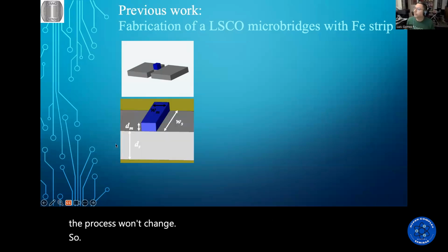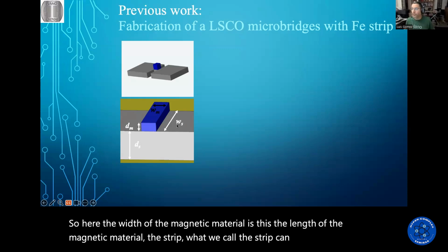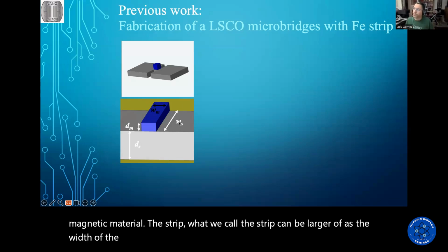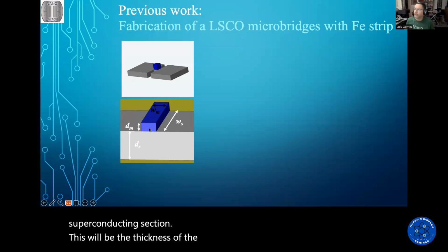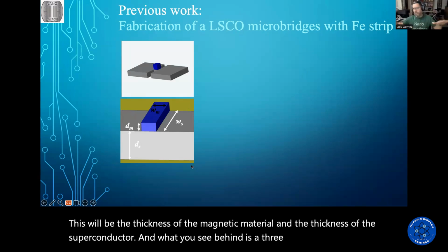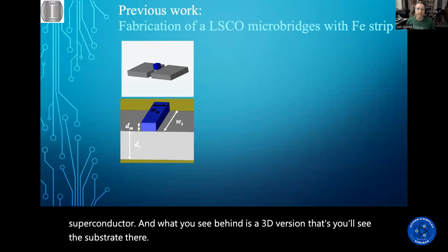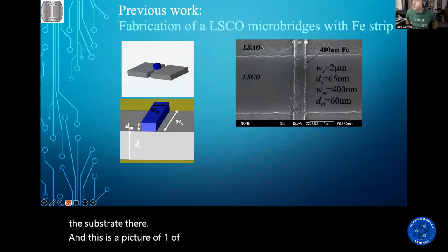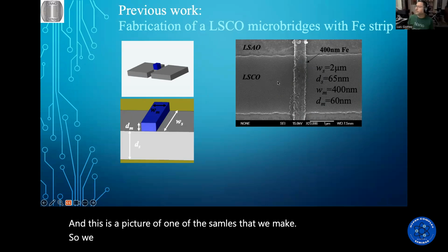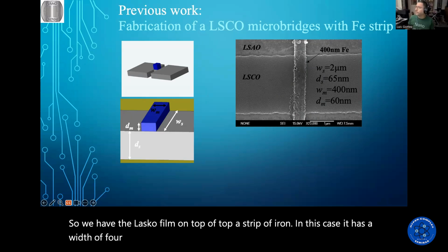So here the width of the magnetic material is this. The length of the magnetic material, the strip, as we call it, can be larger than the width of the bridge. And so this would be WS, the width of the superconducting section. This would be the thickness of the magnetic material and the thickness of the superconductor. And what you see behind is a 3D version. You'll see the substrate there. And this is a picture of one of the samples that we made. So we have the LSCO film with a strip of iron on top. In this case, it has a width of 400 nanometers. This is the substrate, and these are the dimensions as we describe them here.